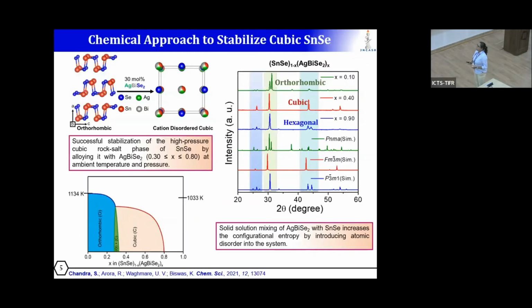So in this work, I have chosen a chemical route to stabilize the cubic rock salt structure of SnSe by alloying with AgBiSe2. AgBiSe2 is hexagonal in nature. When 30 mole % of hexagonal AgBiSe2 is alloyed with the orthorhombic SnSe structure, a cation-disordered cubic rock salt phase is stabilized at ambient condition, which has been verified by powder X-ray diffraction studies. The key point is that solid solution mixing of SnSe with AgBiSe2 enhances the configurational entropy of the system, thus introducing cationic disorder at the tin position and stabilizing this rock salt structure. Further, with DSC and TGA analysis, we could propose a phase diagram of the SnSe-AgBiSe2 system, which is very rare with respect to other thermoelectric systems.